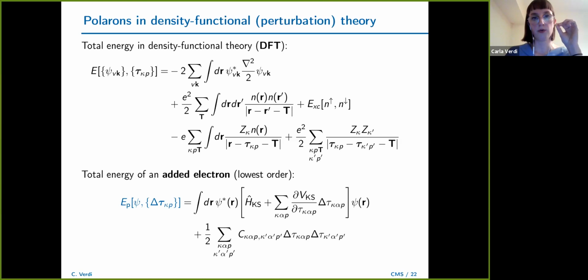So we wrote the total energy of an added electron. We do the same thing as what you would do in an actual DFT calculation. So you add an electron and you write on paper what would be the total energy. But then what we do is to make a couple of assumptions. One is that when we add one electron, the valence electrons are not perturbed. This is an approximation, of course, that needs to be verified, but it's a reasonable one because we're looking at one single electron added in the whole crystal that is ideally infinite.